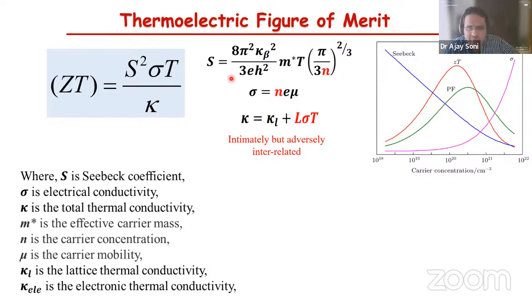And if you look at these parameters, S is the thermoelectric power. This is again a mathematical formulation, so it depends on the effective mass of the charge carriers, and on the number of charge carriers. The rest of these parameters are constants. So there are two different parameters here: the effective mass of the charge carriers, electrons and holes, and the number of charge carriers. Now, the electrical conductivity depends on the number of charge carriers and the mobility of the charge carriers. And this is the electronic charge, which is again a constant.